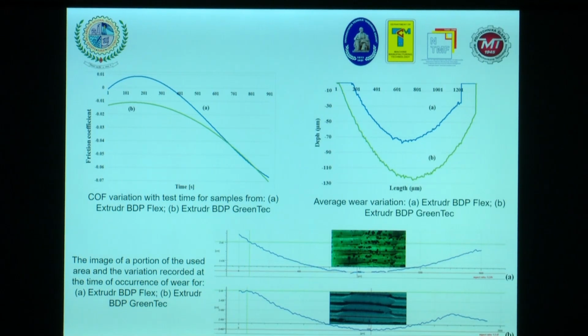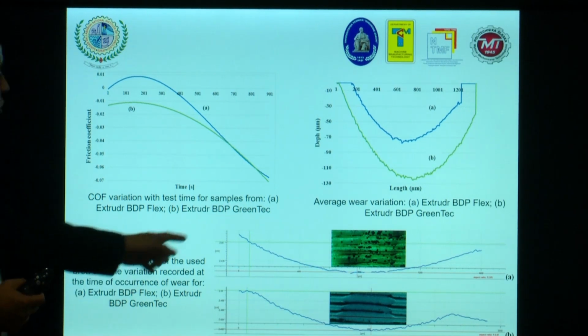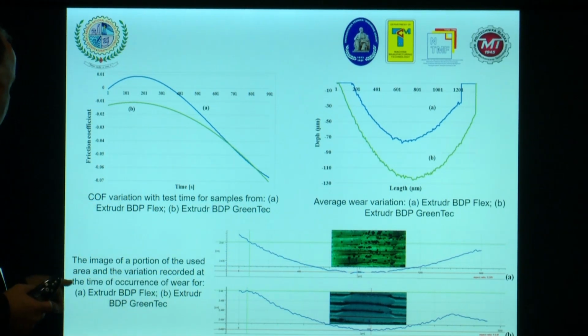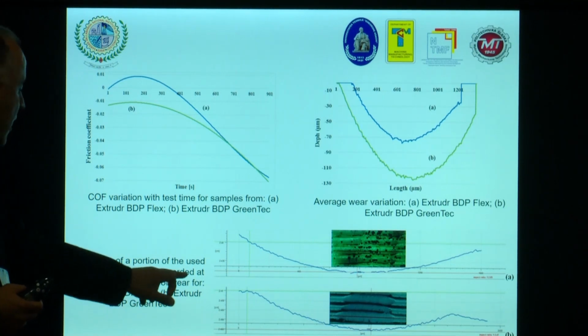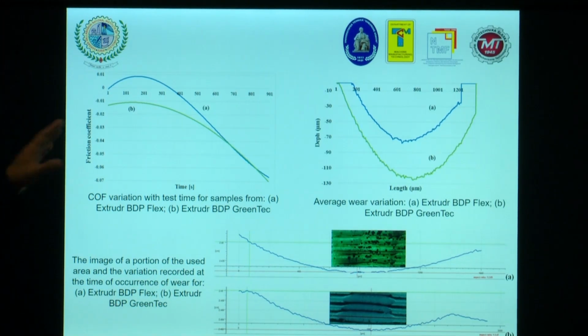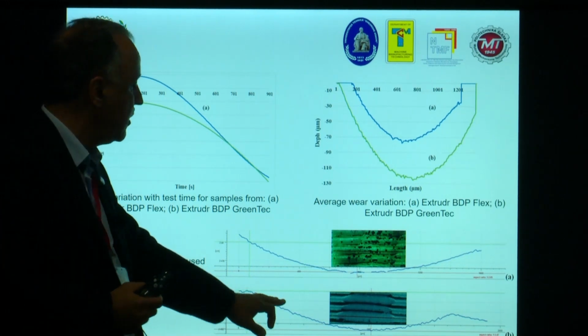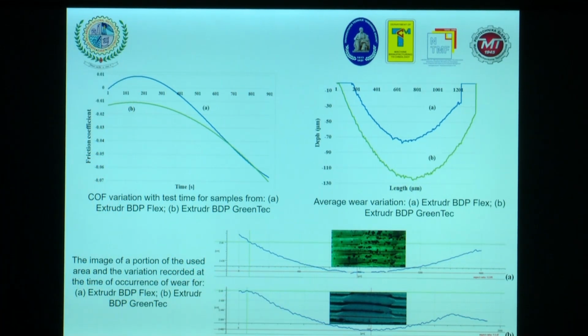The friction coefficient with test time for the extruded sample, you can see on the left. I think the values are very clear, and also the image on the right side of the portion of used area and the variation recorded in time for wear, in case of BDP Flex and BDP GreenTec. Why did we do the wear and the friction coefficient? Because we try to replace some plastic material using one part from our car.